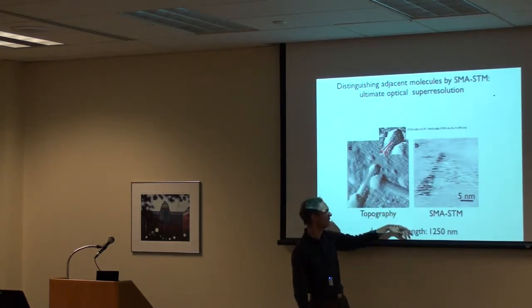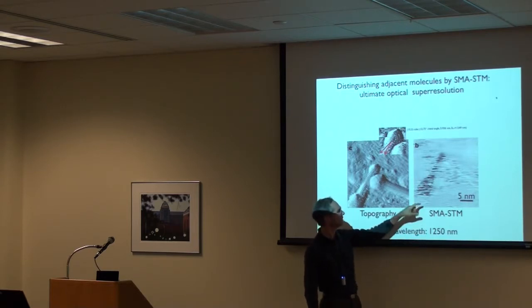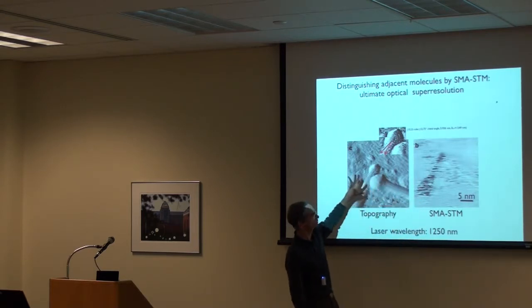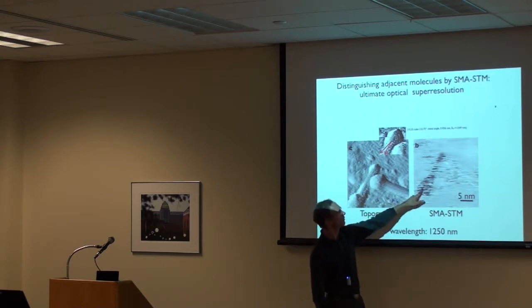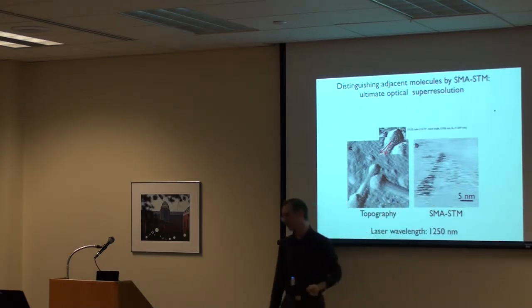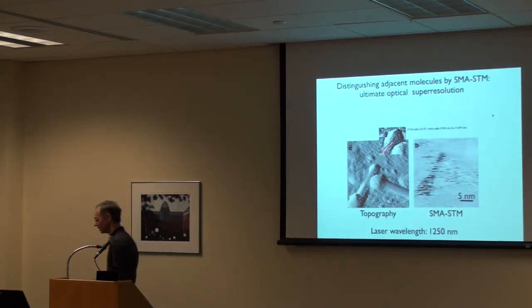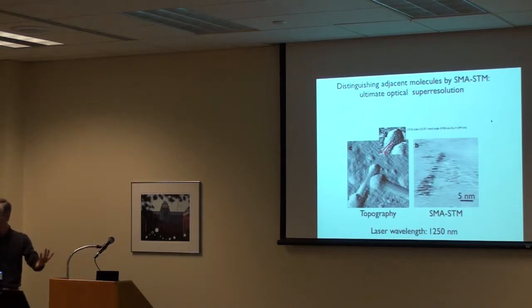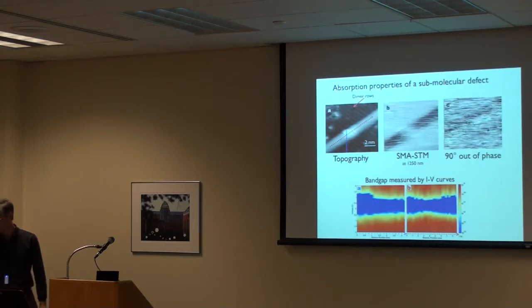And indeed, if we scan in this case to 1250 nanometers, even though those two are sitting right next to one another on that surface, one of them is absorbing and the other one is not. So we can optically differentiate, by single molecule absorption, so to speak, these two tubes that are sitting right next to one another on the surface.